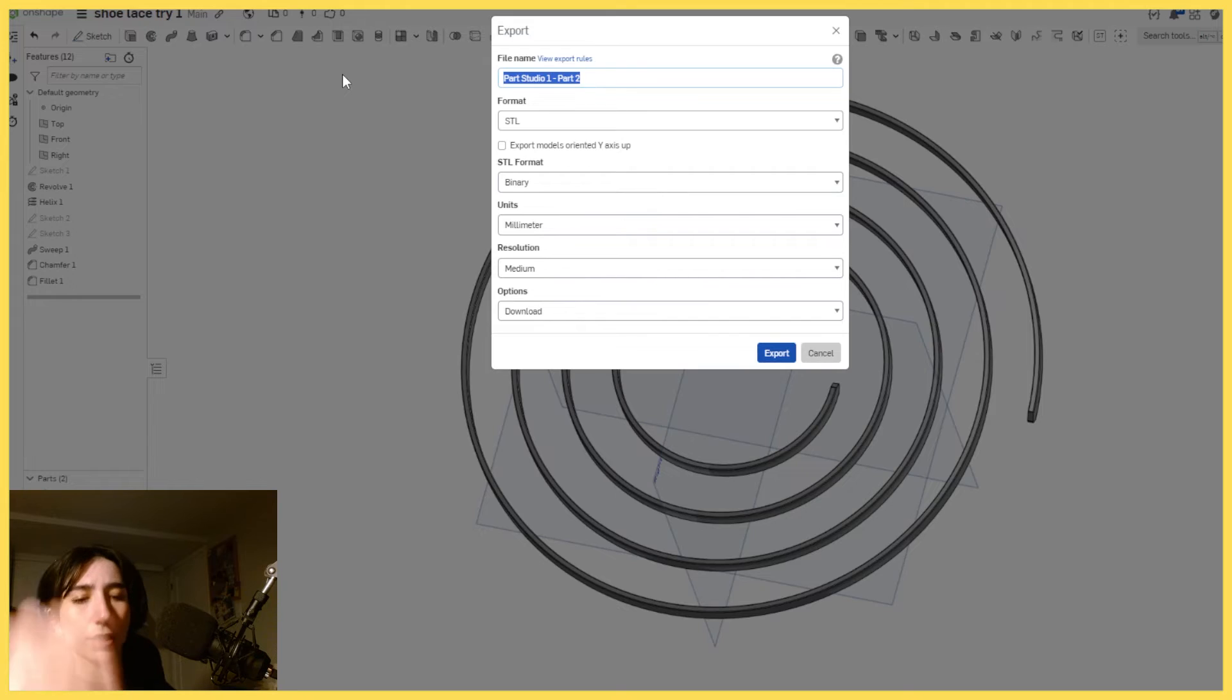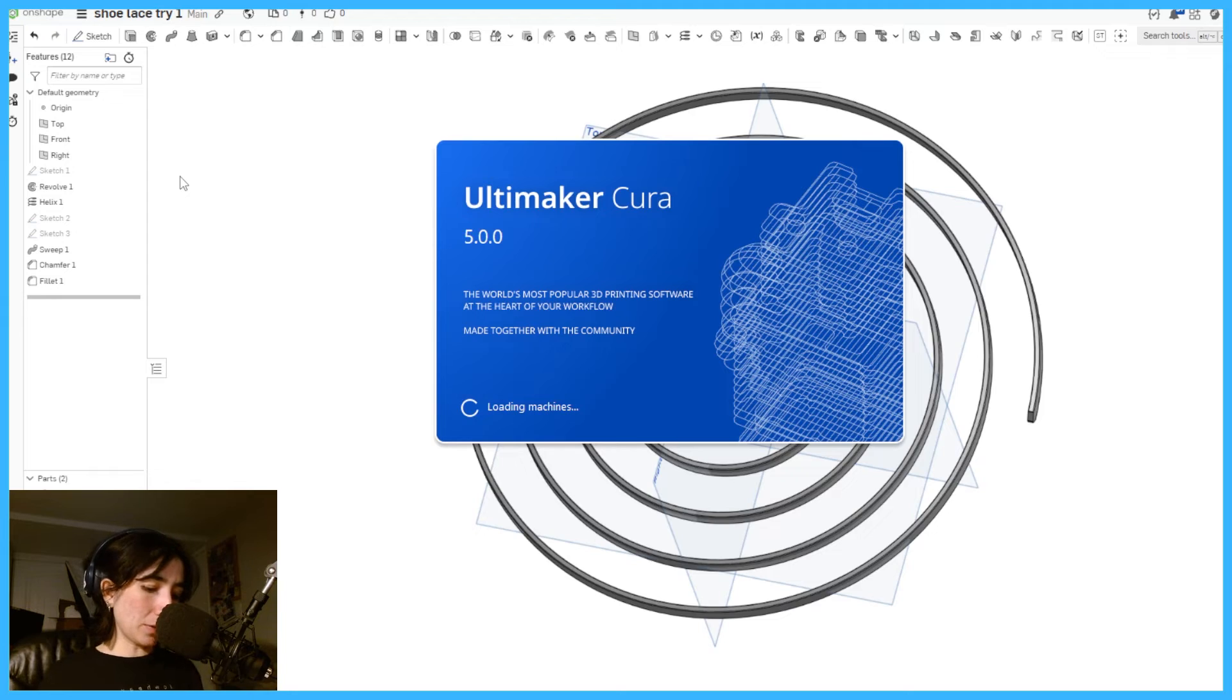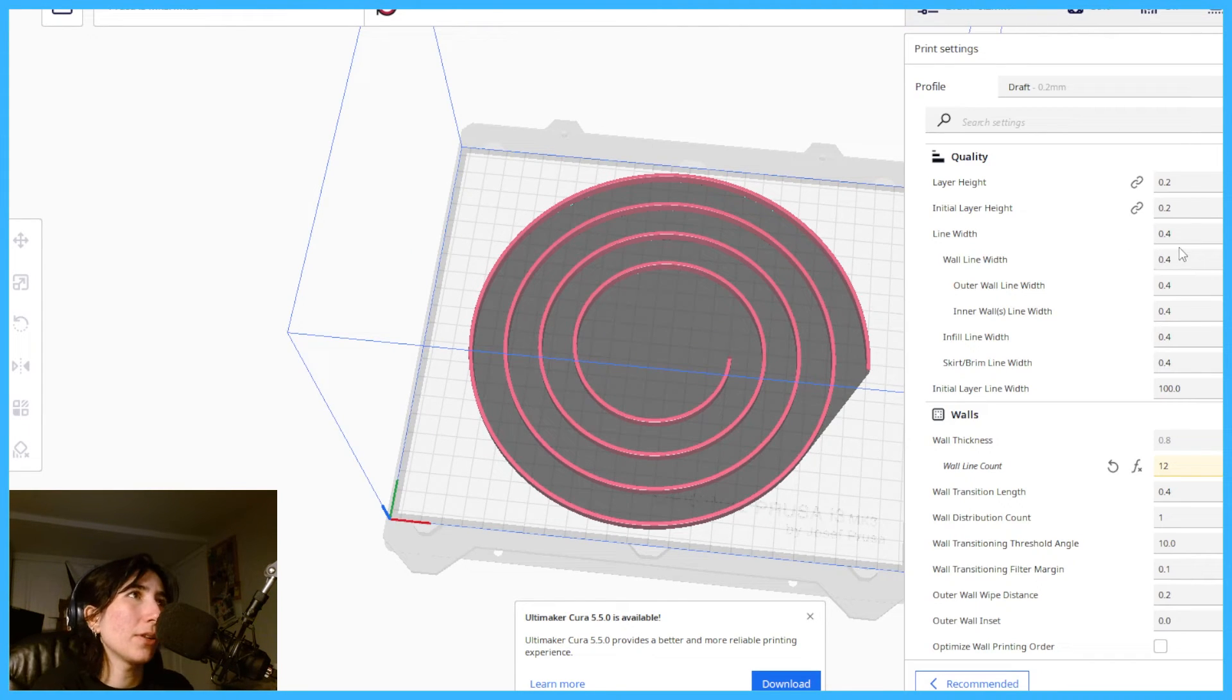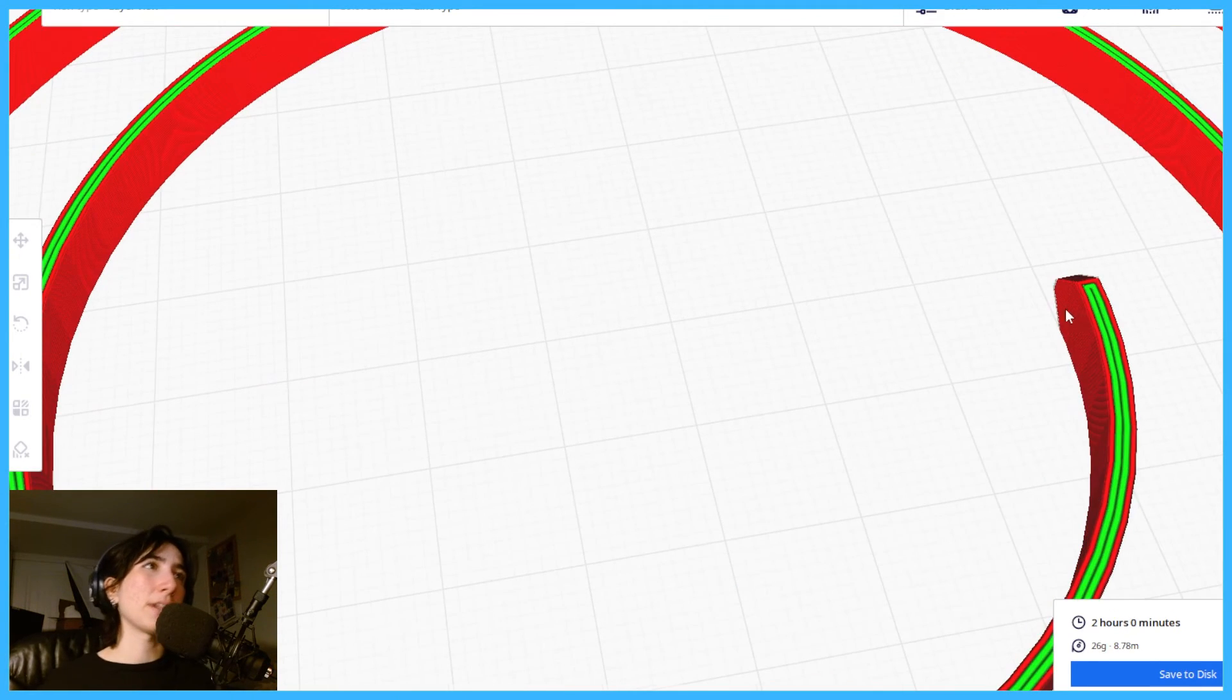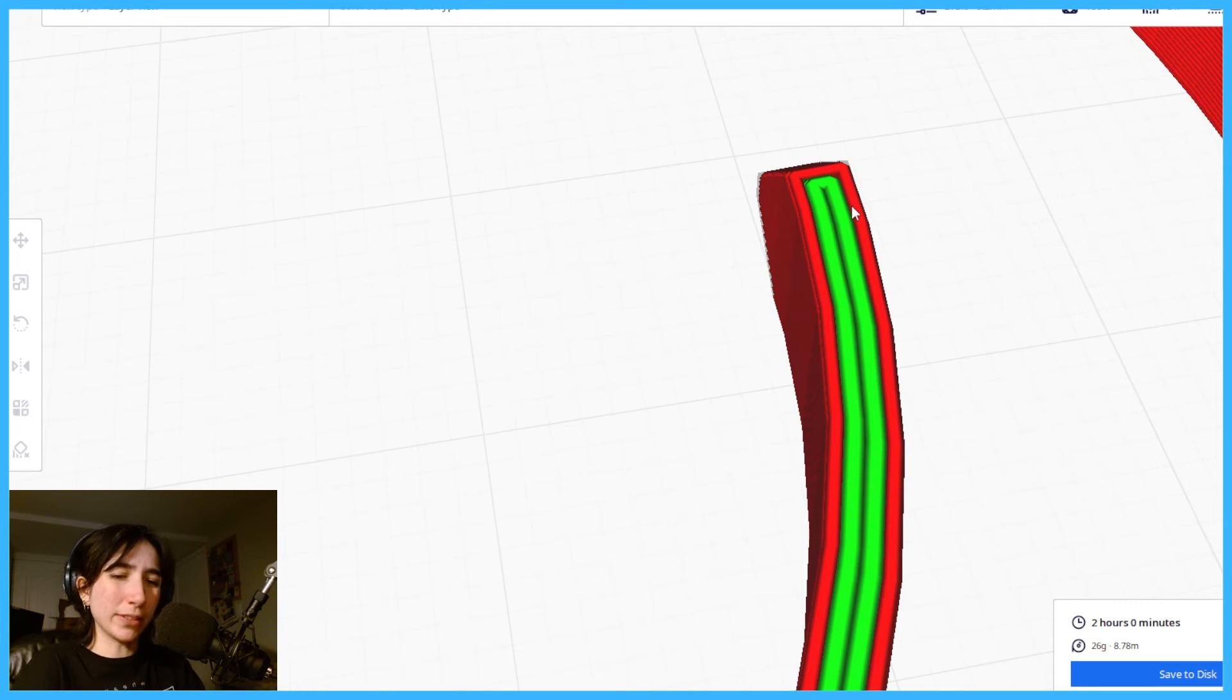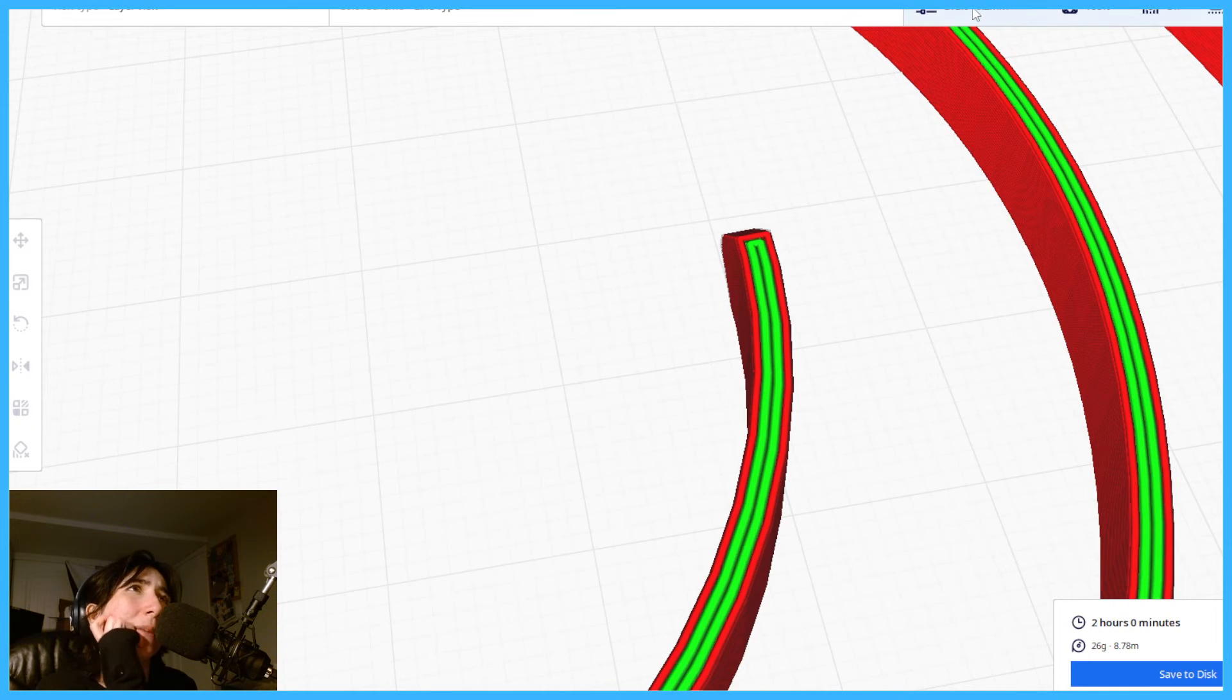Okay, shoelace helix try one. I'm curious if this will actually work. One thing we might need to design is like I mentioned before, a clasp for the lace. I'm curious if I'll be able to tie it. TPU, I think I want to do 100%. It's just gonna take forever to print. Okay, one thing I noticed about printing in TPU is that when you do concentric passes like this it tends to delaminate here, like between wall layers, which I find super odd. Even when I print it at a higher temperature it still does that. I honestly wonder if it's just because my TPU has absorbed too much moisture. Honestly, it's probably that.